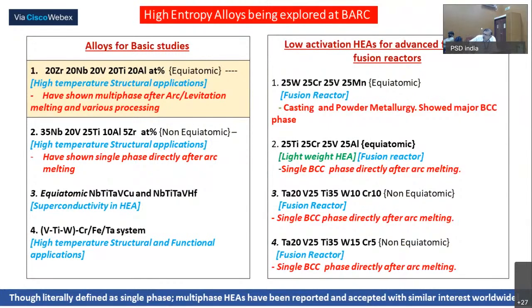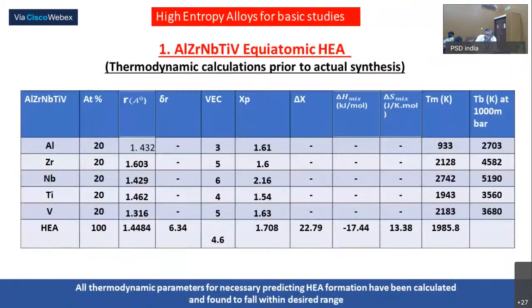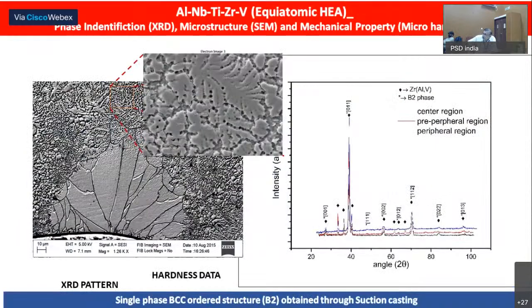For example, let me take you to the first alloy, which I have shown you before. When the thermodynamic calculations were done, all these thermodynamic parameters predicted that it could be a very nice high entropy alloy. So we started our work on that, and the alloy was melted and cast inside a copper cooled crucible so that a high cooling rate could prevail.